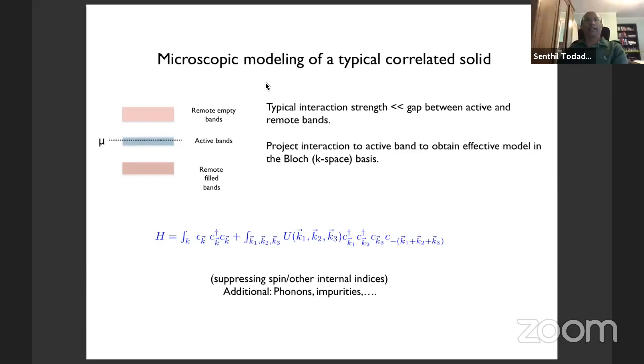So let's now think about how typically in textbooks we model a correlated solid, right? The first thing to do is to think about the band structure. Now there'll always be a bunch of remote, filled bands that are deep below the chemical potential. We don't care about these. There'll also be a set of empty bands that are far away from the chemical potential. We don't care about those as well. What we care about are bands that are near the chemical potential, right? And so long as the typical Coulomb interaction strength is much smaller than the gap between the active and remote bands, the right way to model this solid is to project the interaction to within the active band to get an effective model in Bloch space, right?